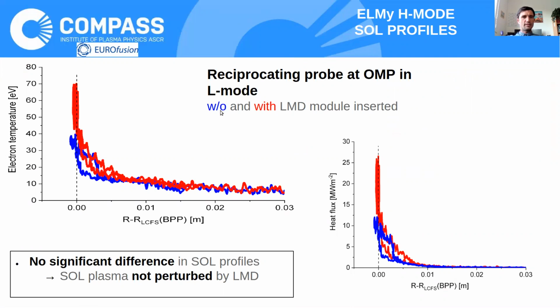Here you can see ELMy H-mode scrape-off layer profiles. In blue color is without the liquid metal divertor inserted, and in red is with the target inserted. And you see there is no visible difference on the electron temperature profile at the outer midplane, and also heat flux. The heat flux is even higher, so certainly the target did not cool the plasma.